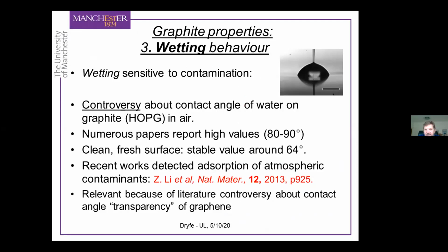And in the context of the Faradaic electrochemistry, I mentioned in particular the sensitivity of graphite surfaces, or the ease with which graphite surfaces can become contaminated in solution environments. And another way of probing that is a completely non-electrochemical way, and that is just through the wetting behavior of graphite. And this has become quite a controversial area in recent years, which might be surprising to some of you.